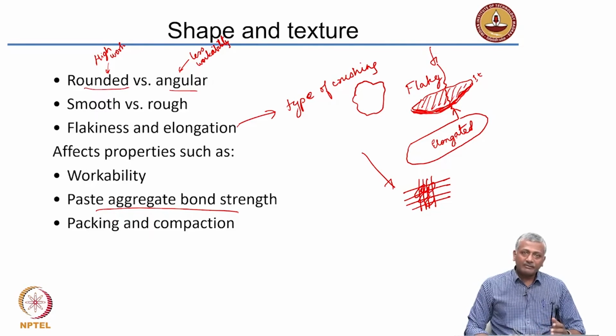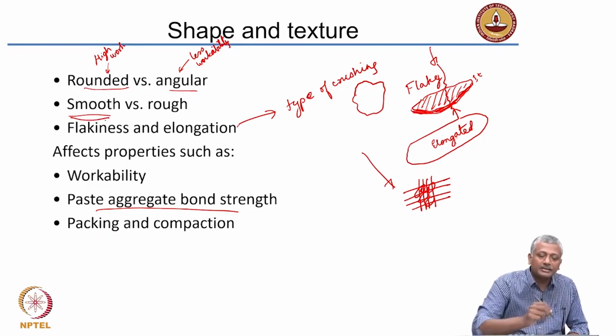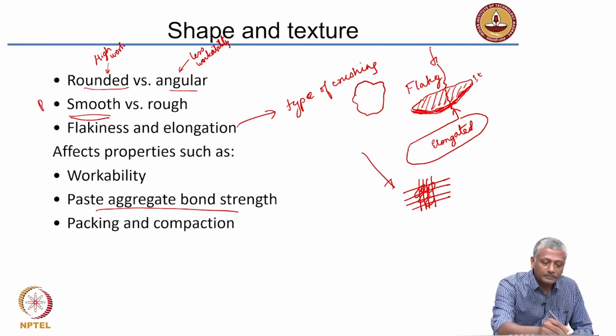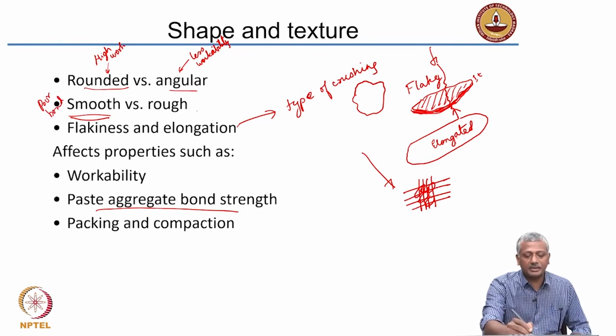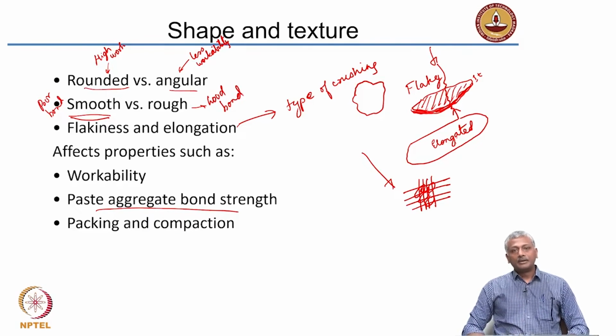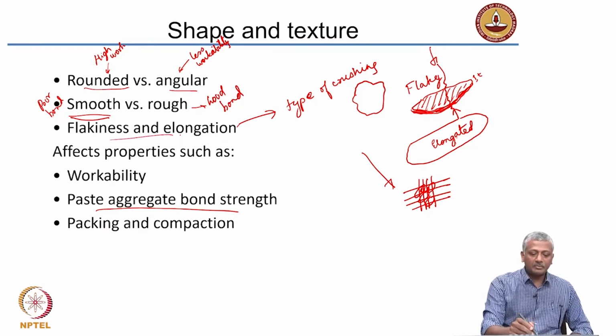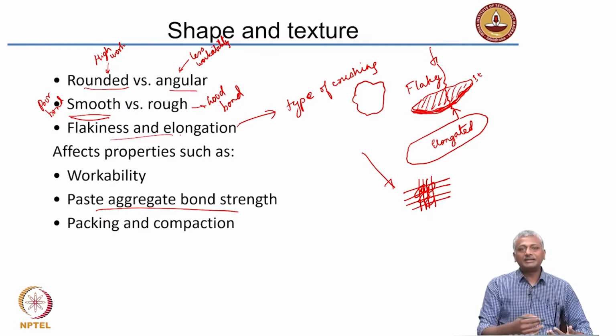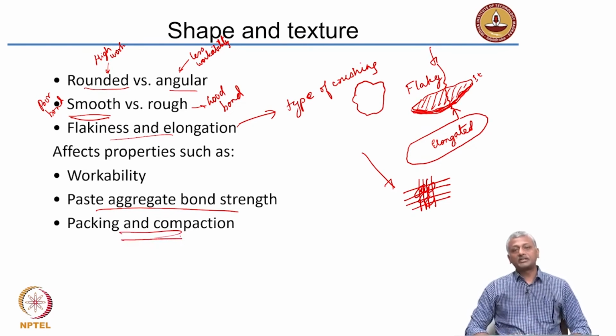So, when you have a good bond, you get high strength. When you have a poor bond, you get low strength. So, generally a smooth aggregate will lead to a poor bond, right? You can clearly imagine that will be the case. A rough aggregate will be leading to a good bond. Okay. And as I said, when you have flaky and elongated material, it will also affect the strength and the ability to pass between reinforcement. Secondly, the packing and compaction will also get affected.